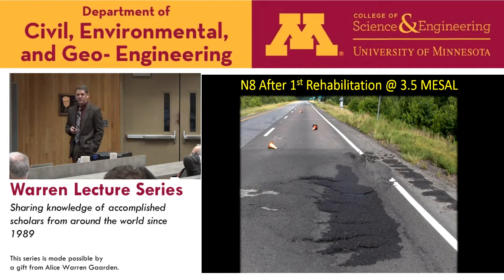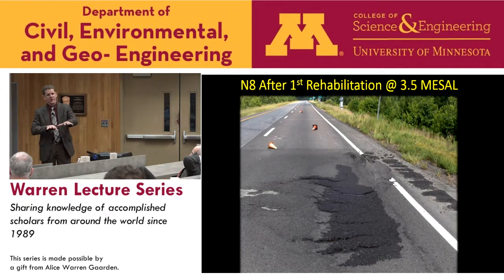We've got slippage failure. There are sections that were literally sliding off of our track. It's a dangerous situation to have, and essentially that paving fabric was put in a very fragile location and created a shear plane and basically contributed to that failure, which is a big problem.